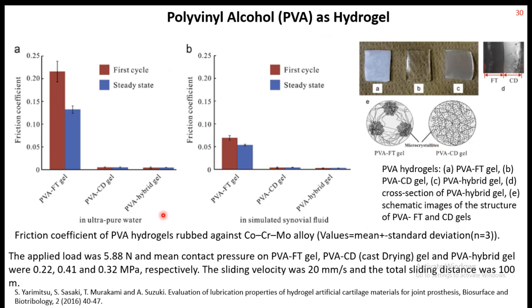Further on, the same group conducted tests with PVA gel, freeze-thaw gel, and cast-dried gel. So just a different way of making these hydrogels, and it was found that PVA CD, which is the cast drying process, gives a better result than the FT. And perhaps the hybrid one will give some better result.